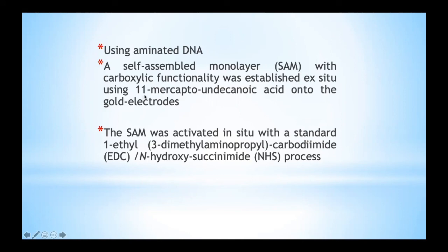In this case, we can use mercapto-undecanoic acid to provide the carboxyl functional group on top of the gold surface, followed by activation with EDC NHS, where we can have an amide bond formed between the carboxyl group and the amine from aminated DNA.